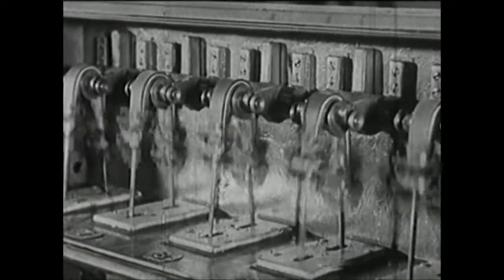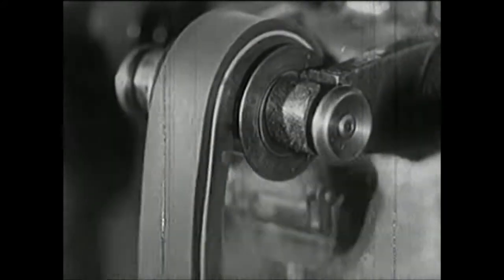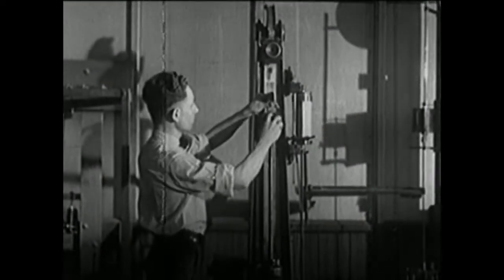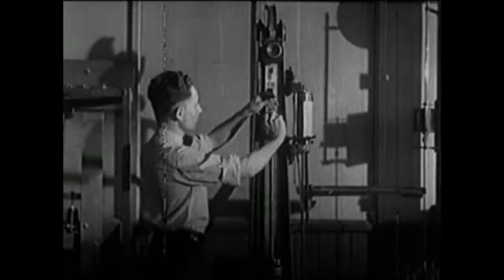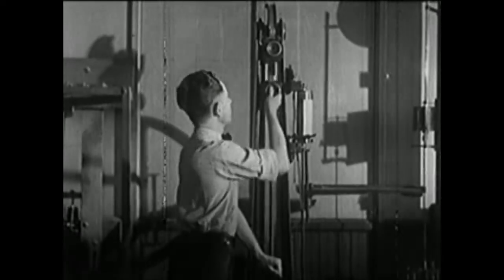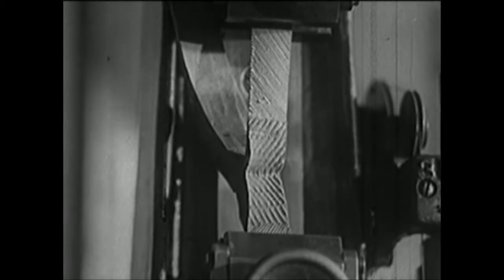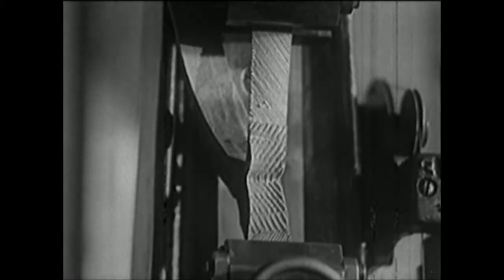Sections of carcass and tread welded together or vulcanized by various experimental methods and compounds are flexed and tormented by specially designed flexing machines to determine their adhesive properties. Other tensile strength machines are used for a pull test to measure the number of pounds necessary to tear the tread from the carcass. This test proves the positive adhesion attained in Brunswick Super Service tires by the double shock absorber unit, not only on a cold pull test, but on heat tests as well.